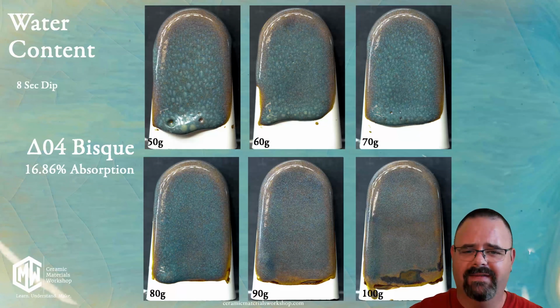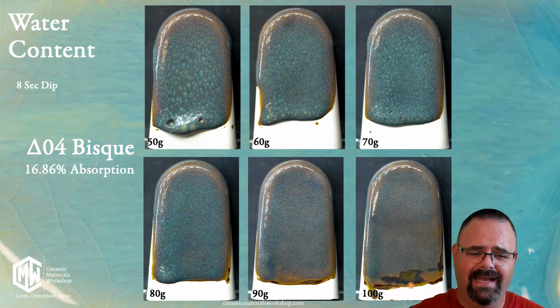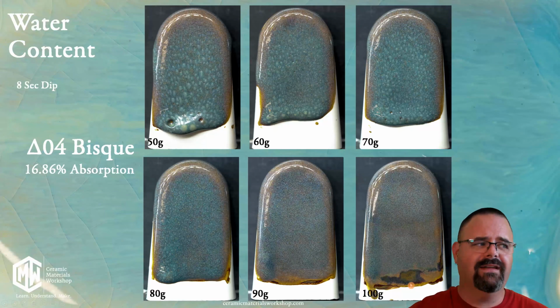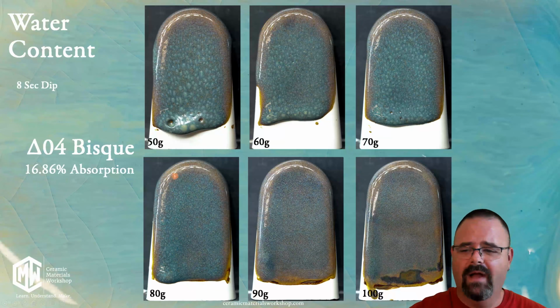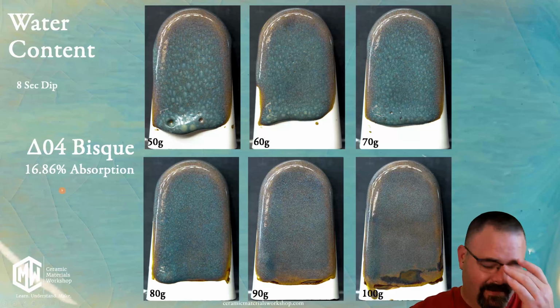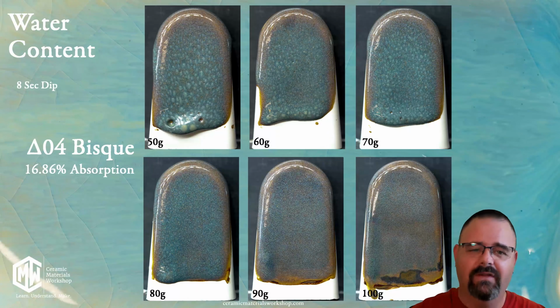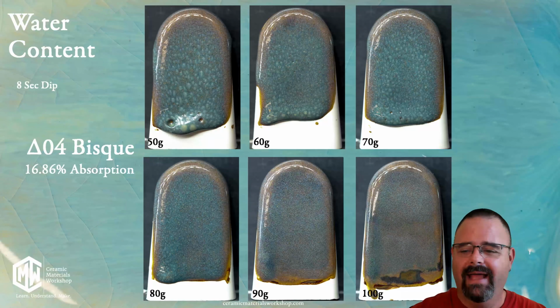And again, we can see with the 8-second dip, it's fine at 50 and it's okay at 60 grams of water, but at 70, 80, 90, and 100, we lose the effect. The glaze application is too thin. Why is that? Well, at cone 04, my clay body has 16.86% absorption, but in the previous slide, we saw that at cone 08, my clay body has almost 20% absorption.